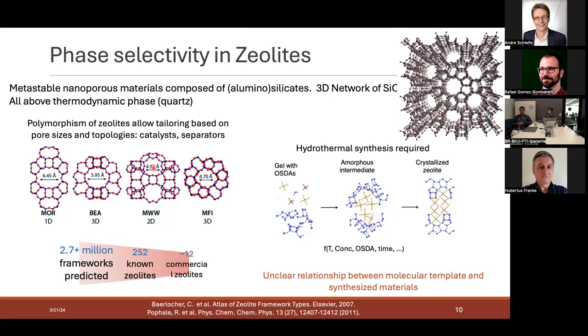Small molecules will go into the pores, and because of the presence of aluminum sites and Brønsted acid sites, fluid catalytic cracking uses these materials to break up heavy fractions of oil into smaller fractions. And if you drive a diesel car, which is less common here than in Europe, maybe, there are zeolites for the NOx. Diesel engines run hotter than gasoline engines, so they produce more nitrogen oxides. Cleaning nitrogen oxides out of exhaust uses zeolites too.